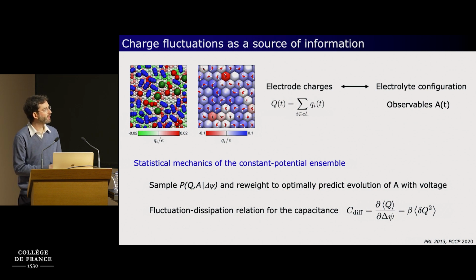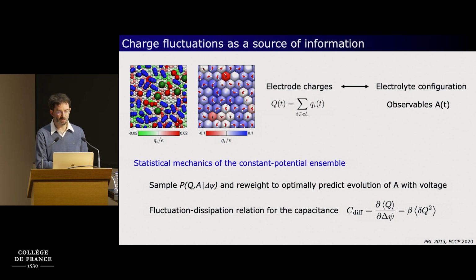And as I've mentioned earlier, you can work out the statistical mechanics of this constant potential ensemble to make a number of predictions. And in particular, we showed that by sampling the joint distribution of the electrode charge with the observable of interest for various potentials, you can use standard reweighting techniques to optimally predict the evolution of the observable as a function of voltage. And we also derived fluctuation dissipation for the capacitance, so the differential capacitance, which is a derivative of the average charge of the electrode with respect to voltage.